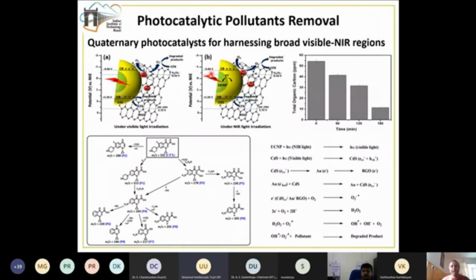On the other hand, when we use the NIR light, the NIR light has a good penetration power. So it can penetrate through the cadmium sulfide, which is a thin shell, and reach the upconversion nanoparticle, and interact with it, leading to the emission of a green light, because we have the ytterbium and erbium combination. This emission is shown here as an energy transfer, ET. And this energy transfer leads to the promotion of an electron in the cadmium sulfide from the valence band to the conduction band, and that does this entire photocatalytic activity. This is the mechanism under the NIR light irradiation.